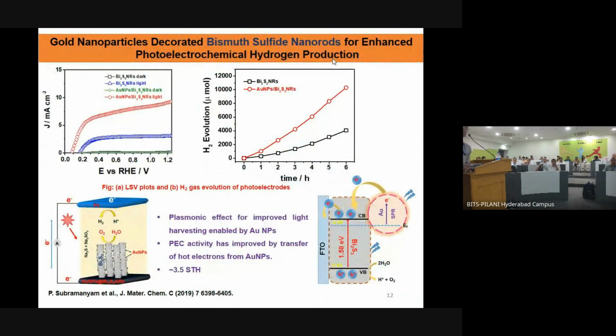If you try to decorate them, you can actually see that, mostly if you look at bismuth based materials, which are also known for thermoelectric materials, because of the nature of these materials, they can also be active under dark. Okay, so if you look, they are not very active under dark. Then the moment you shine the light, you look at the current density improves. And at the cathode side, or counter electrode side, you can now estimate the hydrogen which is evolved. I am only talking about a cutoff region of 1.5 electron volt, which is nearly the cutoff.